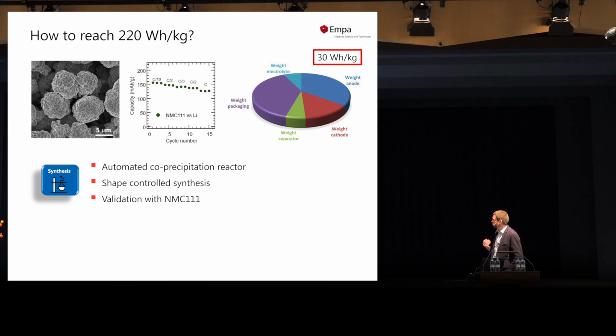So in a first approach, we validated our synthesis routes, trying to synthesize this NMC111 material. This stands for nickel, manganese, cobalt in a ratio of 1:1:1. These are layered oxides with lithium inside. These were commercially available already 2 years ago. And so we had basically a comparison, how good is our material compared to what is established on an industrial level.